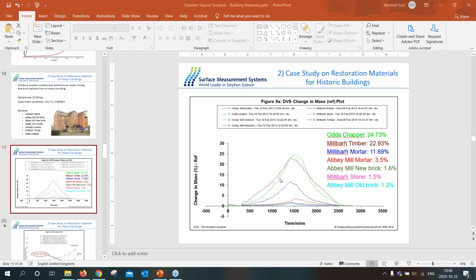Yeah, there are certain materials. Wood is one of them. Of course, the geometry makes a difference, and like Meishan mentioned earlier, if the samples are powders or sawdust, for example, the equilibrium will establish much faster than for just a chunk of the same wood. But there are ways: by changing the carrier gas, for example from air to nitrogen and nitrogen to helium, the diffusion would improve slightly. I can't say that it'll improve massively, but you will reach equilibrium faster by using helium. On the other hand, it's expensive as a carrier gas.